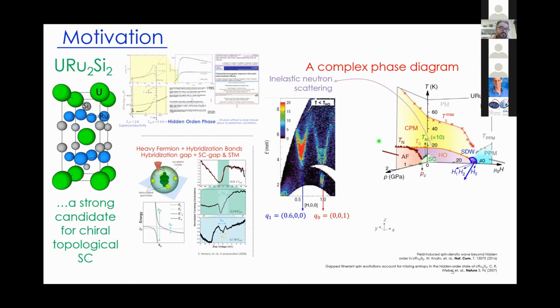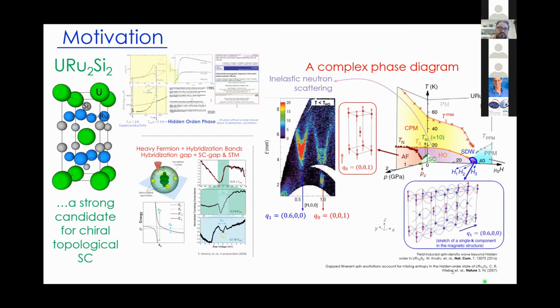Now, the phase diagram of this system is very complex, and here I just want to show one of them as a function of the pressure and the temperature. In the hidden order phase, neutron scattering experiments have shown that there are two dynamical spin excitations, identified with these two vectors, Q0 and Q1. These vectors also identify other regions of the phase diagram. For example, the antiferromagnetic region is identified with the same vector Q0. And at high magnetic fields, above 30 Tesla, another magnetic phase is identified with the Q1 vector.